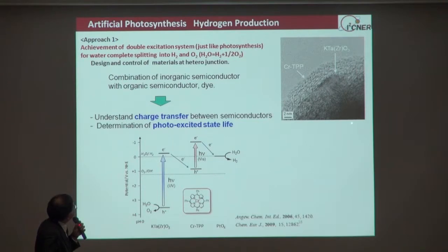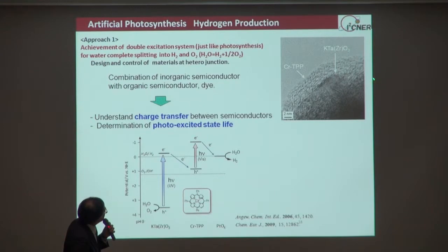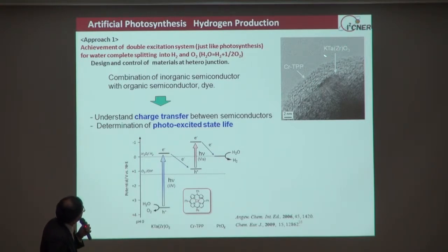In order to do this, we used a very unique catalyst, with an inorganic semiconductor inside and covered with an organic dye outside. This is a TEM image, and as you can see here, the inside is highly crystalline KTaO3 perovskite, and the outside is covered with chromium tetraphenyl porphyrin. This thin layer is coated on the surface of the perovskite, and as you can see here, the structure is highly oriented, and therefore self-organization of this organic dye is achieved on the surface of the inorganic catalyst.